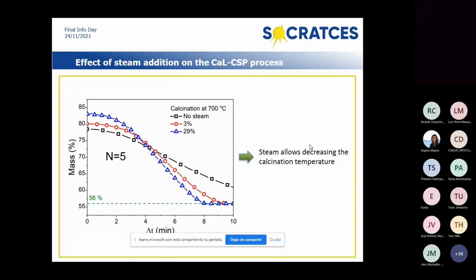Well, the interesting thing concerning the application to the CaL-CSP process is that using steam we can decrease the calcination temperature in order to attain full calcination in a shorter time. So it can be seen here that with the use of 29% of steam in volume, we were able to decrease the temperature up to 700 degrees. In that condition, we were able to attain full calcination in less than 10 minutes.